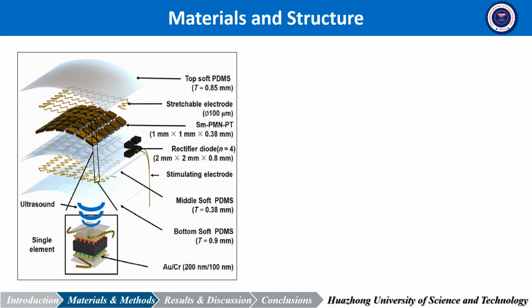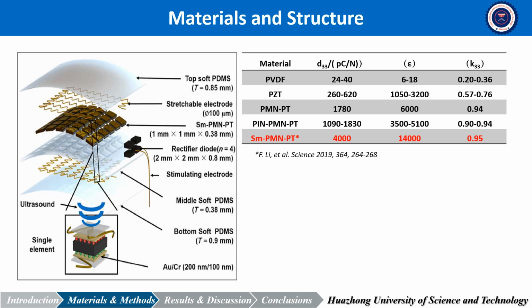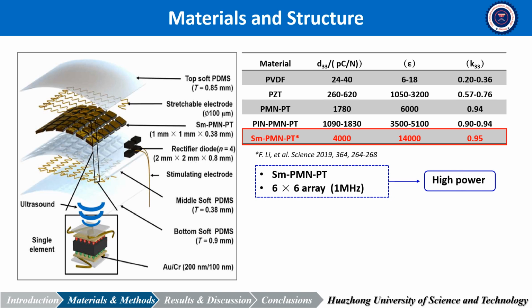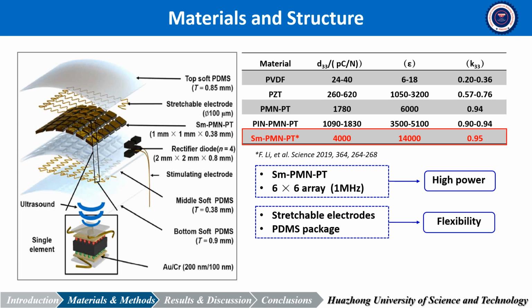As we have analyzed before, for the device fabrication, the material selection is very important. Compared with other piezoelectric materials, samarium-doped PMN-PT single crystal owns the largest dielectric constant and the largest electromechanical coupling coefficient. So we selected this kind of material, and the resonant frequency of this material is set to be 1 MHz. To further increase the output power of the device, we design a 6x6 array structure. Additionally, to facilitate device implantation in vivo, the flexibility of the device is achieved through stretchable electrodes and PDMS package.